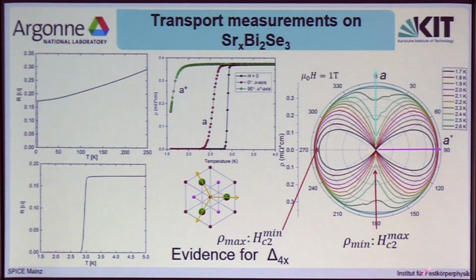So you can also, of course, then do the full sweep in the plane. And you can see here the axes are indicated. So again, the minimum in resistance is the maximum in HC2, or the maximum in the gap function. And the maximum in resistance is the minimum in HC2 and also the minimum in the gap. So this would be clear evidence for the delta 4x realized in this sample. Of course, you can orient your crystal and you can measure the upper critical field. However, it would be nice to have some more direct evidence of which gap is actually realized in our system.